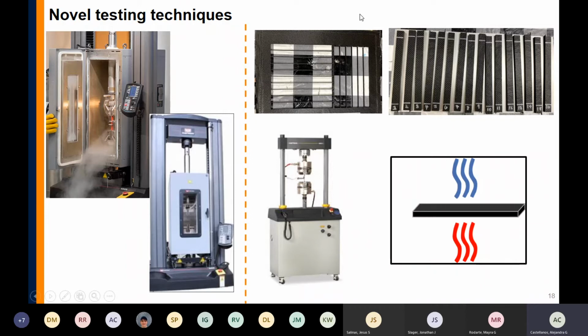So what we are doing, as you can see here on the top, those are some samples that my students manufactured. And this is the laminate from which we took those samples. For this laminate, we use our water jet cutter. So we figured out a way to expose one side of the composite to a given temperature and the other side of the composite to another temperature, to mimic what a real scenario will look like.